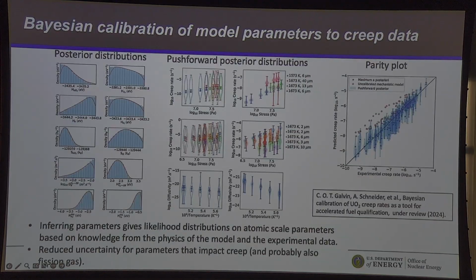Again, we go through uncertainty quantification. As good as the model is, and we do that from only what we call first principles, so we don't directly involve experiments. It would not be a good approach to throw away experimental data when you have them. So by picking some of that data and improving the model through these uncertainty quantification frameworks, we can get a model that reduces the uncertainty from these big bars here to these smaller bands here. And this just shows that for a number of different conditions and data points.